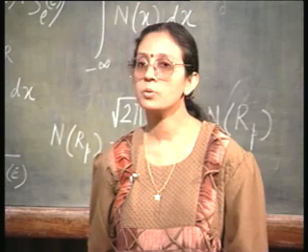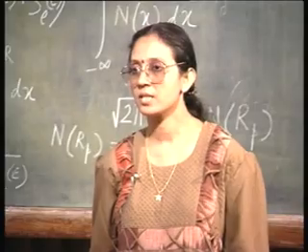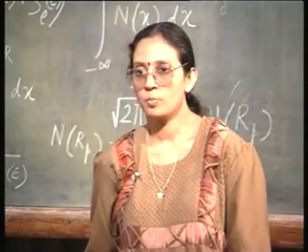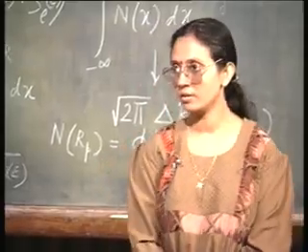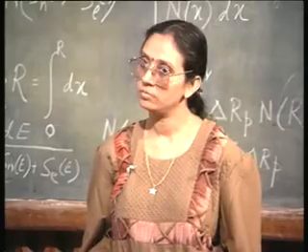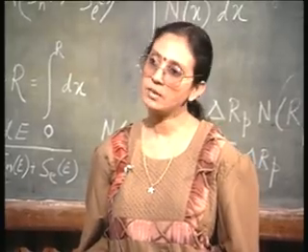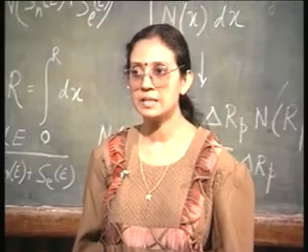Why are you doing that? You are simply creating disorder on the surface. The surface is getting amorphized, so that your profile is going to be more Gaussian. It is going to resemble a Gaussian function more. Okay? There is another way of resembling an amorphous target, and that is